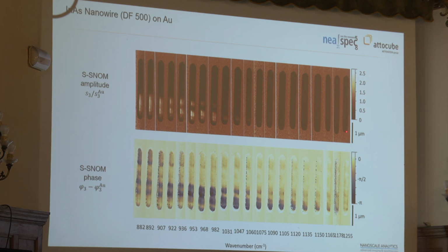Let's go from here. At very high frequency, it's not reflective. But at lower frequency, it starts becoming reflective. So this means very likely there's a charge carrier response here. And the point where this turns on, the contrast, is different. So here, we see already something here, but at a different nanowire position, contrast turns on here. So the charge carrier concentration will be lower here compared to here on the wire.